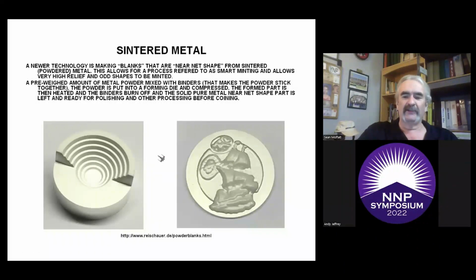And a kind of newer technology I just want to touch base on is sintered metal. Basically, you can make near net shaped blanks, which are close to the final shape of the coin or the metal that you're making. This allows for a process that's called smart minting. It allows for really high relief and just odd shapes to be minted. A pre-weighed amount of the metal powder is mixed with binders to make the powder stick together. That powder is put into a forming die, compressed and formed into a part that is then heated, which causes the binders to burn off. Then the solid pure metal, which is near the net shape of the finished part, is left and ready for polishing and other processing before coining. We'll touch on this process a little bit later.